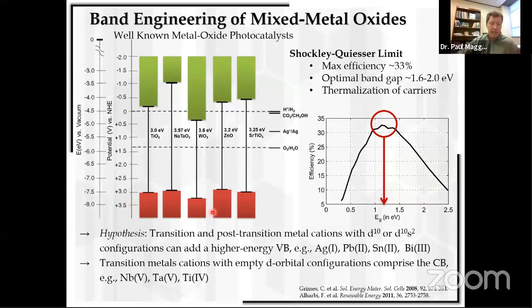What's not changing here, however, is that oxygen valence band edge. And if you want a highly efficient solar energy converter to make chemical fuels from sunlight, you want a band gap that is not as big as 3 to 4, right? To reach the maximum efficiency of 33%, you need an optimal band gap for absorbing the light, because it's a balance of carrier thermalization as well as having a small enough band gap. There's an optimum region of around 1.2 eV, right? But you need to add in the overpotentials to drive those half reactions at the surface. So an optimal band gap is typically estimated to be around 1.6 or 2.